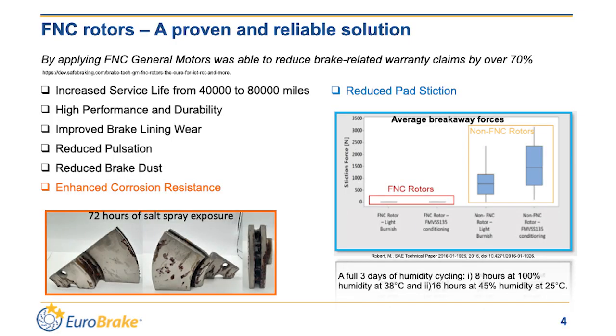Using FNC on brake rotors is a proven technology. It was used for the first time by General Motors. They found that they increased the service life from 40,000 to 80,000 miles. They reduced the brake wear and the pad wear. They reduced the pad stiction, and this was confirmed by other different studies. One of them is presented here.